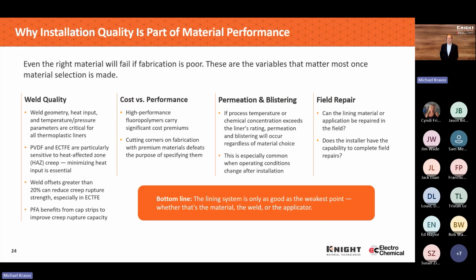Yeah. Additionally, field repair. Something's been in service. It's working. There's a problem. Is the system designed where you can get in and repair it? With the sheet lining materials of vessels, we need to have access when we actually do the lining to be able to go inside, get our hands on everything, and line it. Certain technologies, again, rotolining, which is a good technology, may give you the ability to line the vessel in one piece without having a manway access, which sounds really good on the front end. But if and when there's a problem, you can't get in and inspect it, and you can't get in and repair it. So you're stuck with an expensive reline for the entire thing instead of a repair.